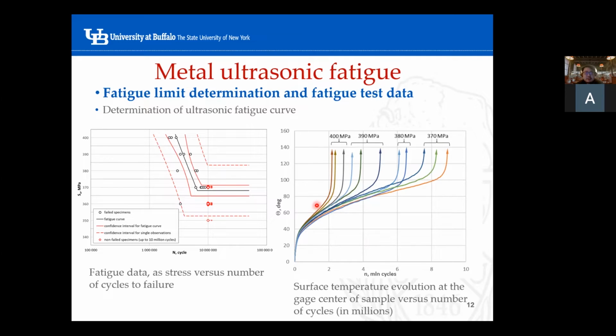However, in ultrasonic vibration fatigue, we have an initial high temperature increase followed by an almost linear steady temperature increase, and finally a rapid temperature increase in the final stage. So this temperature evolution can be divided into 3 different phases.